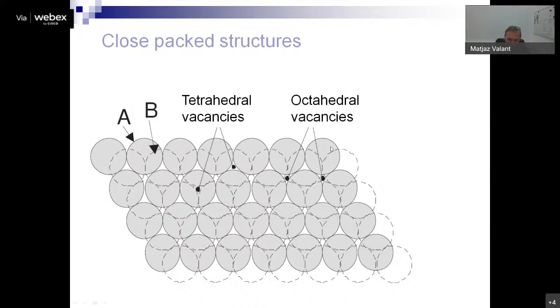So if we assume now first one layer of these particles, which here is denoted as an A, this layer can pack as it's shown here. These are circles, full circles. Basically, it's a central ion surrounded by 6 other atoms. And this is the close packed 2-dimensional structure. But when we bring this into 3 dimensions, of course, we can put on this layer another layer of atoms. And there's only one way we can put this layer B on the top of the first layer, as it's shown here.